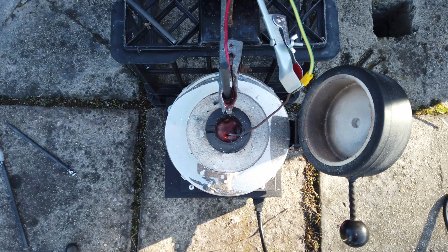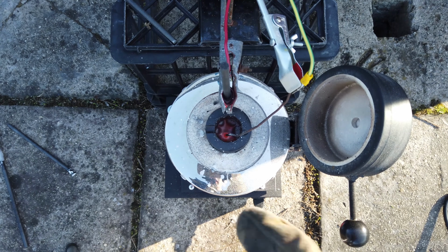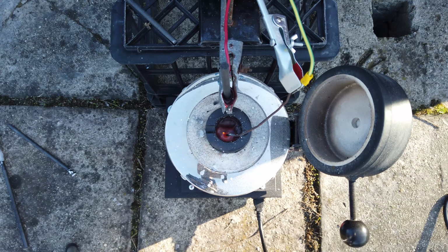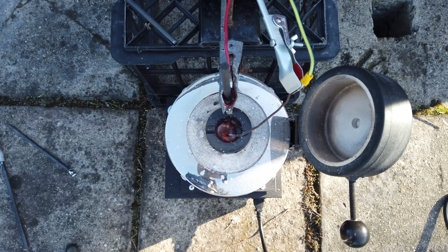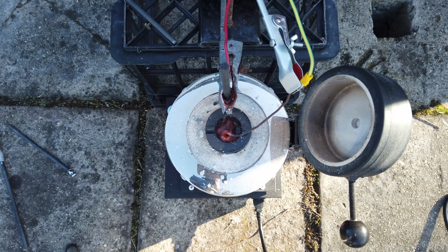Alright, false alarm actually. Upon turning the cell off and taking the electrodes out, when the cell was being allowed to cool down, I found a small shiny globule of calcium metal floating in the molten calcium chloride melt. So I've set the cell back up. We're going to try this again. I'm going to leave this running at 8-9 amps for another 10-15 minutes.